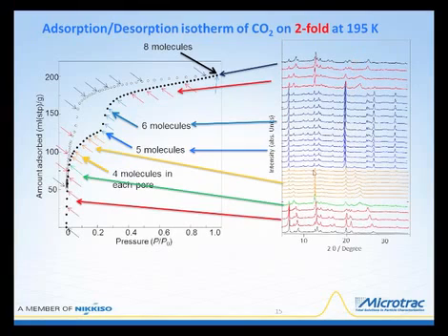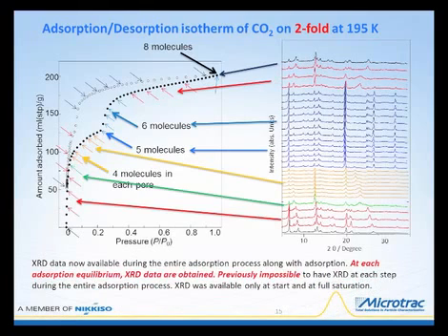And we can now start to get kinetic information as to these changes and what can be expected. So now the XRD data is available during the entire adsorption process. At each adsorption equilibrium, XRD data are obtained. Previously, again, the only thing that would be obtained would be to take the sample and then expose it to a chemical, CO2 or benzene or something else, and then somewhere along here take one point, and then the whole process would have to be repeated time and time again. And this type of instrumentation and the integration of adsorption with XRD allows this all to occur automatically with some controls imparted in the software.